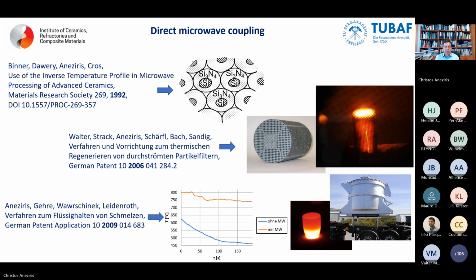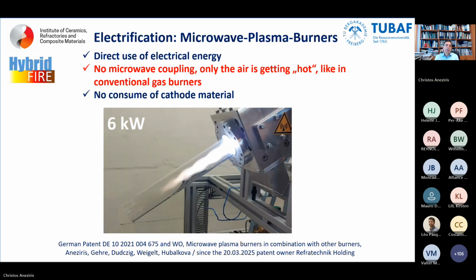In the past, we have used the direct microwave coupling, for instance, for making silicon nitride, reaction bonded silicon nitride, or to couple the soot in a diesel soot filter to burn it out to regenerate the diesel soot filter. Or we have seen also the positive impact if you have already a melt, like an aluminum melt, you have an interaction with microwaves and you can keep the temperature, and so the melt can be transported on the motorway from the melter to the end user. Yes, we want to use microwave plasma burners because we can directly use the electrical energy. We do not have a consumption of cathode material, and the most important is we do not have a microwave coupling. It's only the air that is getting hot, like in conventional gas burners.